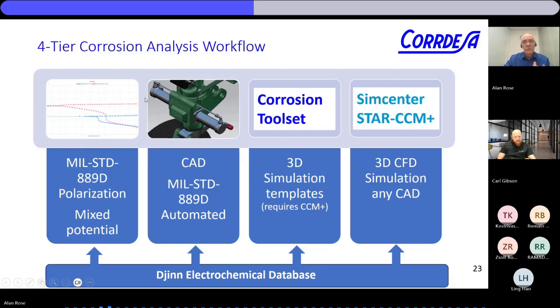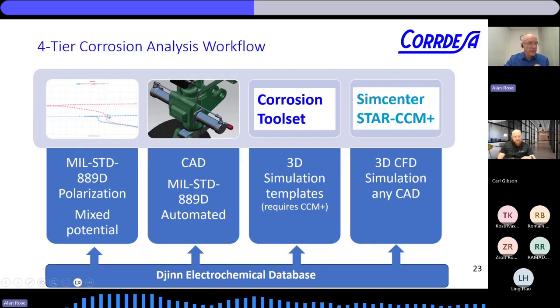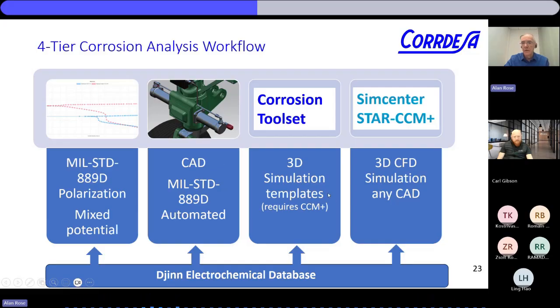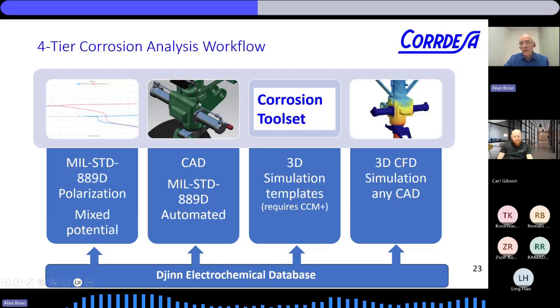And then we incorporated this capability into a CAD system. So in the CAD system, the CAD will automatically look for all of those interfaces and apply the mixed potential theory to all the materials either side of the interface and come up with a color code table of your corrosion risk inside of that CAD file. Then if there's anything risky in there, you can change the materials within the CAD system. If that doesn't remove it, maybe you need to do a redesign, and then there's a way of looking into the details.